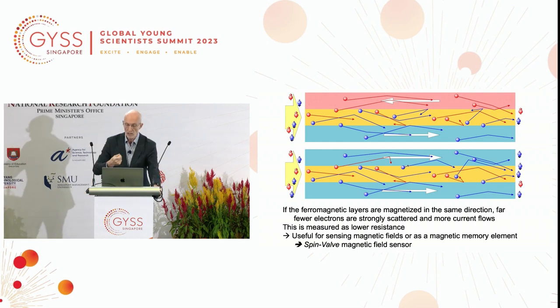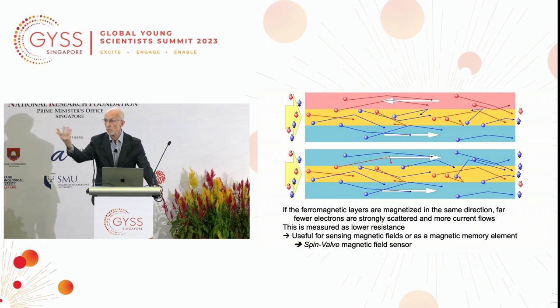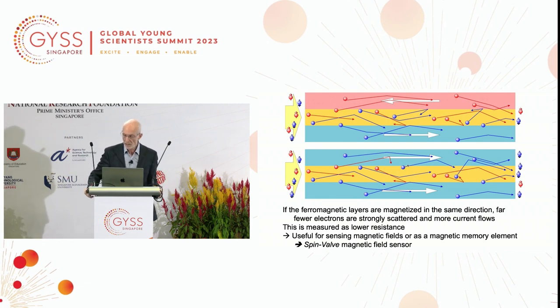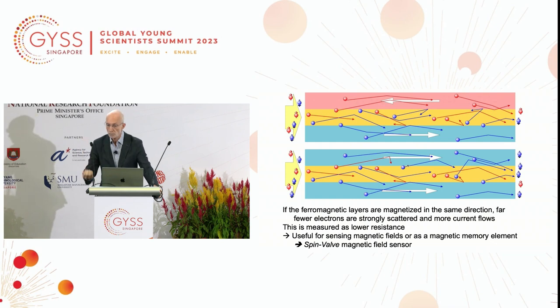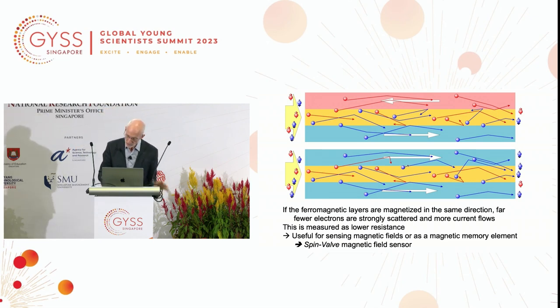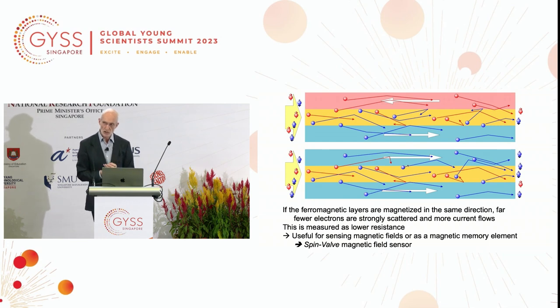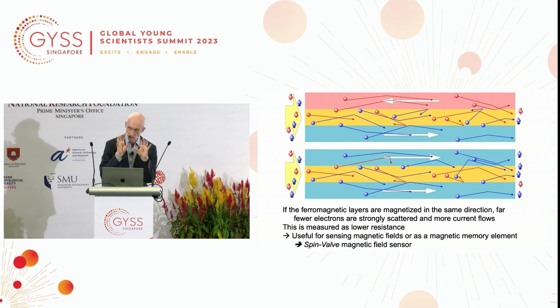Now this phenomenon of spin polarization of the current was actually proposed in the 1930s by Neville Mott. Neville Mott won the Nobel Prize for an amazing series of discoveries. When I was a student in Cambridge, his office was opposite the region where I was building and exploring transition metal dichalcogenide magnetic systems. Nevertheless, the change in resistance in the structure is only 10%. Nevertheless, this device I proposed as a sensor to detect magnetic fields, to detect the magnetic regions in a magnetic disk drive, and we could do that 10,000 times more sensitively than any other device that's known even today.